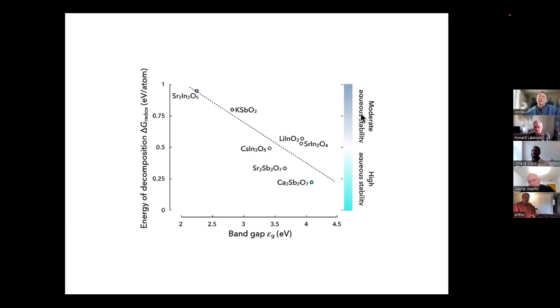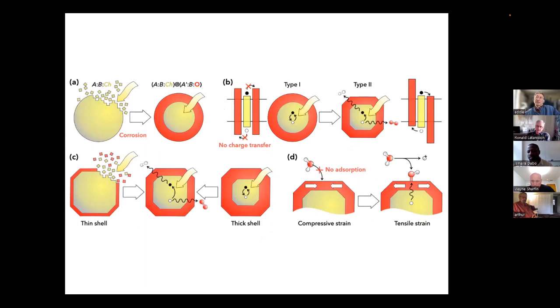So there's this trade-off that emerges intrinsically from our calculation. That there is this competition between absorbing solar light and being stable in water. And so that's not good for us, because what absorbs solar light then will decompose and dissolve in water. So one of the strategies, and this is very much a proposal that we submitted last month, we would like to combine those two, essentially having a transparent core that would protect a light absorbing shell.